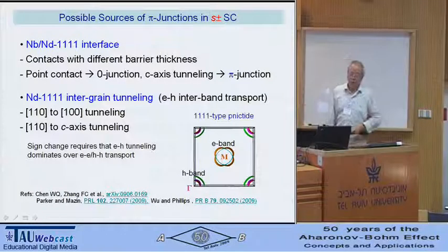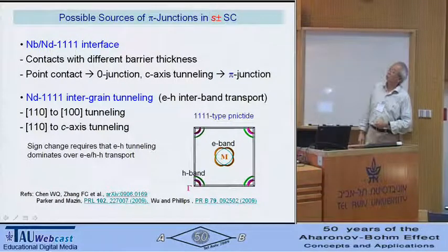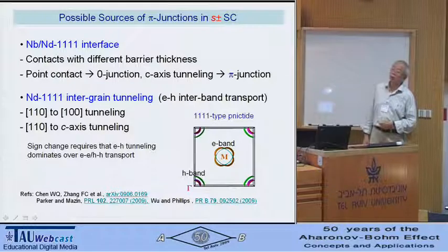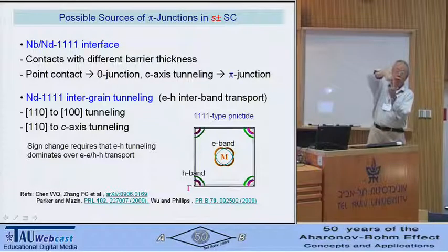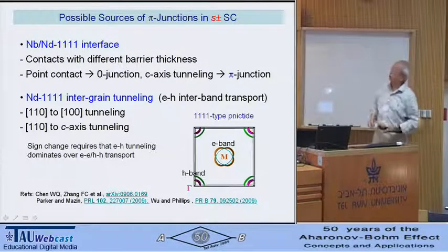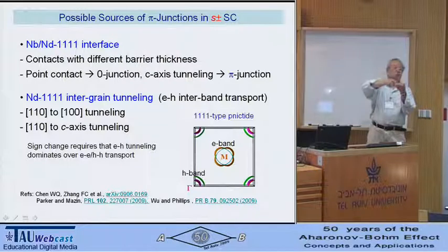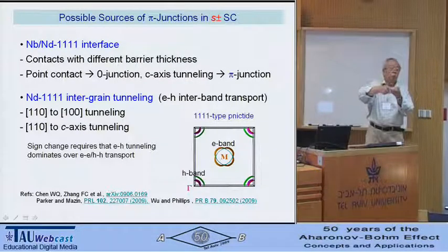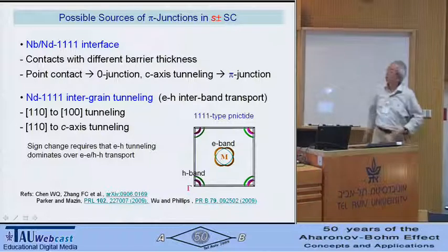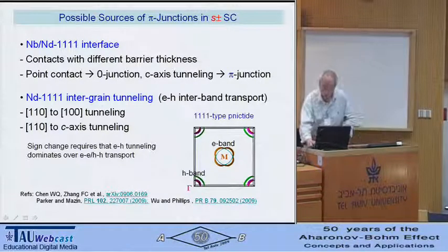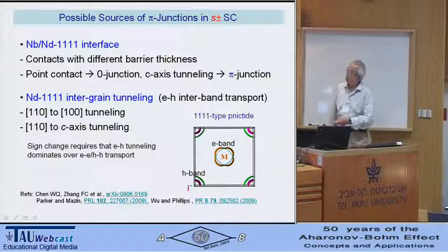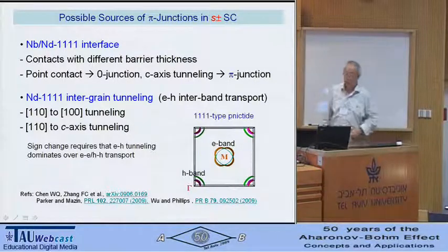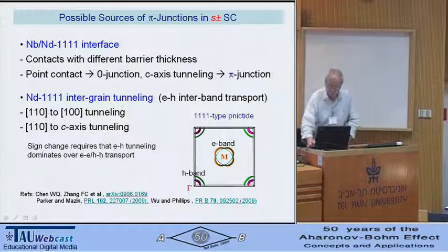Oh, if you are interested, you can find out what the possible sources of a pi junction are in this experiment setup. We say there are two possibilities. One is at the niobium iron pnictide interface. In other words, this is the point contact right at the contact. The other is in between the contacts. There is polycrystalline material. You could have a sign change over there. So those are the two possibilities. And in the literature already, there are some papers discussing such possibilities.